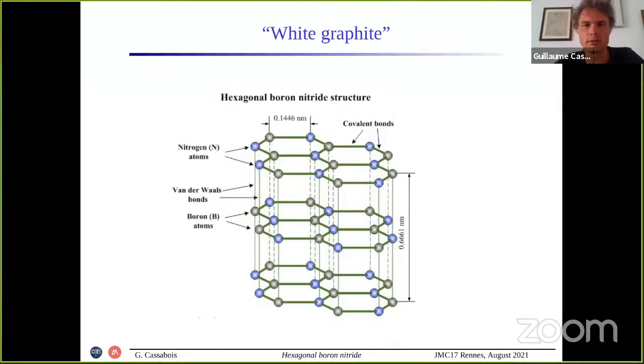So what is the microscopic structure of hexagonal boron nitride? It's very similar to graphite, and it is often called white graphite. So it is made of boron and nitrogen atoms organized in honeycomb lattices. So we have 2D planes made of boron and nitrogen with quasi-covalent binding between these atoms. And hexagonal boron nitride is the vertical stacking of these 2D layers. And in between the layers, there is this weak van der Waals interaction that makes the material 3D. So we have this very strong anisotropy in the electronic binding, with van der Waals interaction between the layers, and covalent binding within the layers organized in this honeycomb feature. So it's very similar to graphite.